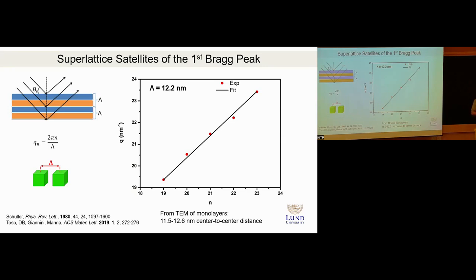Can you tell again what is the difference between the blue and the orange? Just the density. So it's two different materials. But in this case you have perovskite with two different densities. So you have a perovskite nanocrystal, you have organic ligand in between, and then you have another perovskite nanocrystal, with ligand in between. Yes, so it helps to create the contrast in electron density that then produces this interference. So 12.2 would be twice the oleic acid? So 12.2 nanometers is a center-to-center distance between nanocubes. So if nanocubes are 10 nanometers, then 2.2 would be whatever is in between.